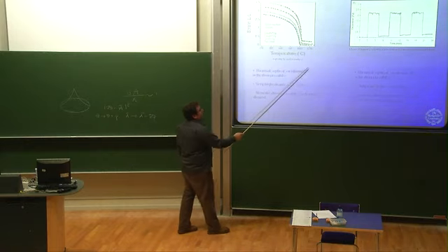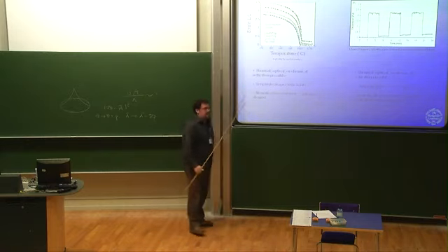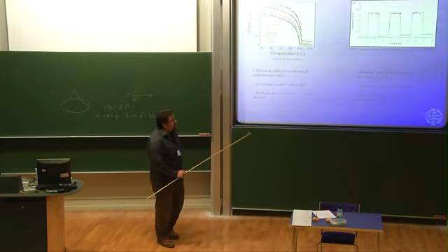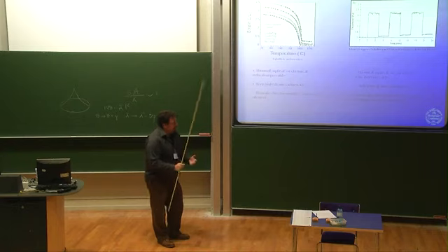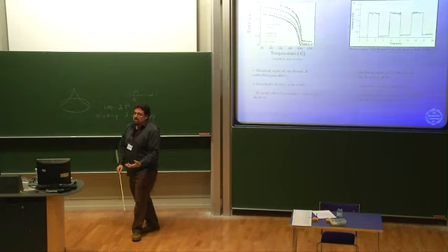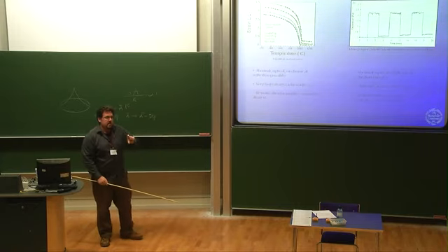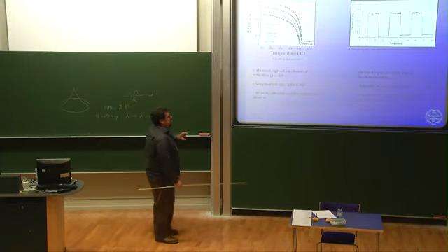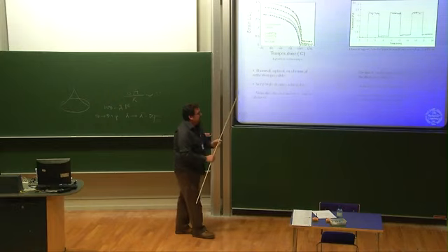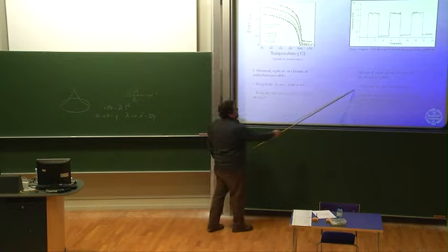So luckily, the other class of nematic solids, the nematic glasses, solves this problem. It's essentially a polymer glass where you just greatly increase the density of the crosslinks in the system. And so the director becomes immobile because of the much constrained motion of the polymer paths. You can only hit relatively low strains.